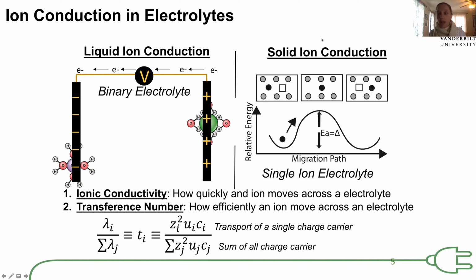But if we implement a solid ion conductor where ion transport in a solid occurs through the presence of vacancies or defects, we only have a single charge carrier. And so we can have a transference number that is equivalent to one. And typically the ionic conductivity in a solution is much higher than that of a solid. But recently there has been significant work in the inorganic materials chemistry community to come up with many, many families of solids that are showing ionic conductivity similar to liquid electrolytes.